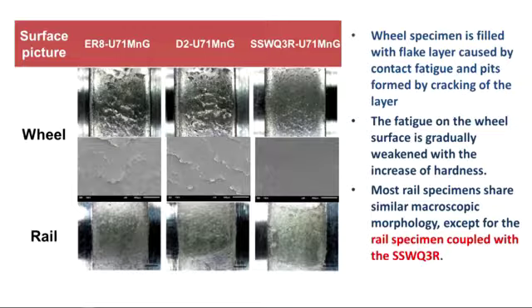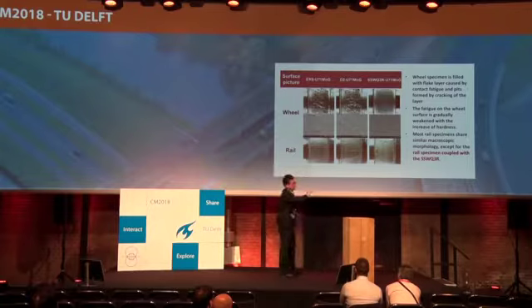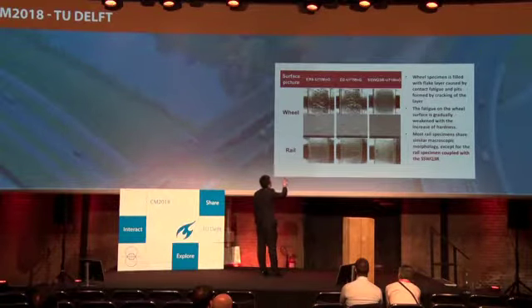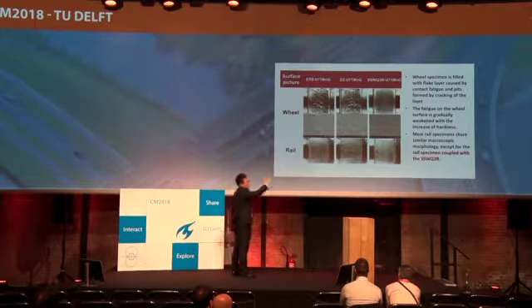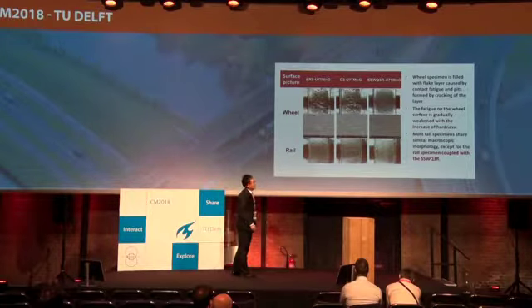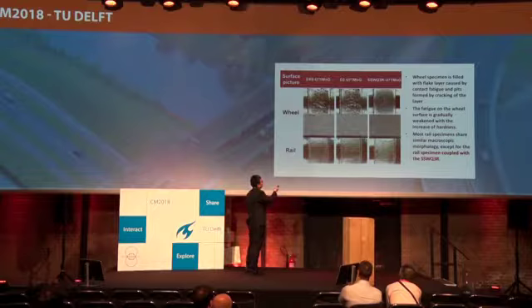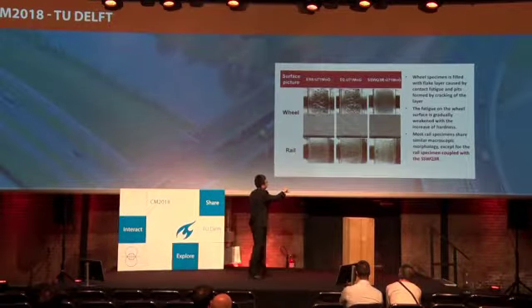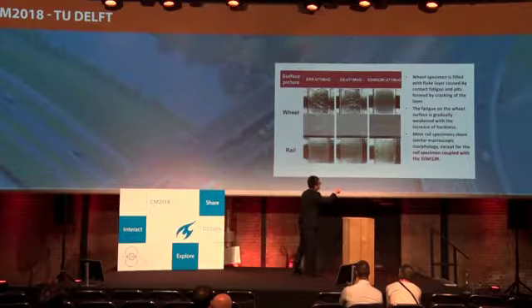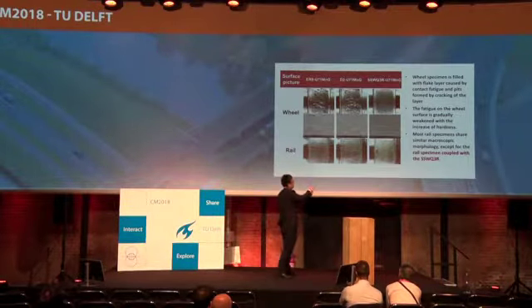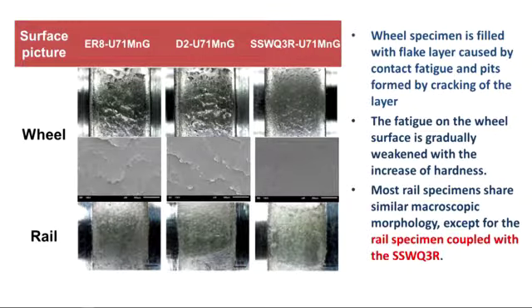In the figure, we pick up 3 out of the 5 wheel materials, because we can briefly divide them into 3 hardness levels. So we make the order as the hardness level, and the right is the hardest, and the left is the softer. So as we can see, the surface becomes smoother as its hardness grows. And for the rail specimen that counters the wheel, most rail specimens share similar macroscopic morphology, except for the rail specimen coupled with the hardest wheel material, which is SSWQ3R.